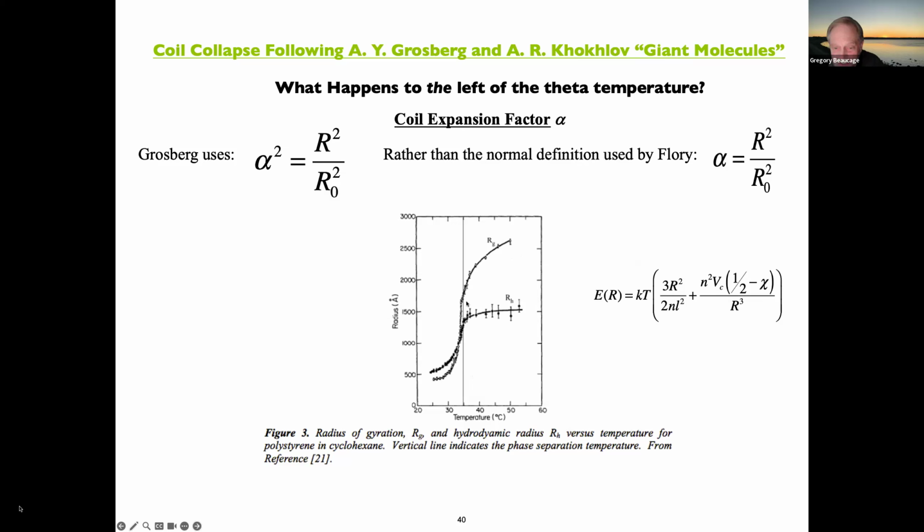But that doesn't have to be the case. It can be the case that you cool it down and then there's a step change. In that case, there's an enthalpy associated with that step change, a discrete volume change. If you take the derivative of volume, the thermal expansion coefficient, it's infinity when it's a step change. And here it's an actual value that changes through this transition.